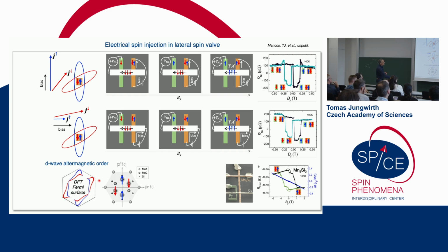And this is the orientation of the D-wave order with respect to the crystal lattice, which are aligned with the device. So it's all aligned in the proper way. And so what you see here in this biasing geometry, which is, let's say, the ordinary biasing geometry, is that there is different magnitude and slightly different deflection angle between the up and down spins, right? But in total, in the horizontal direction, you will have majority spins pointing down, the red spins. So you inject spin polarized current.